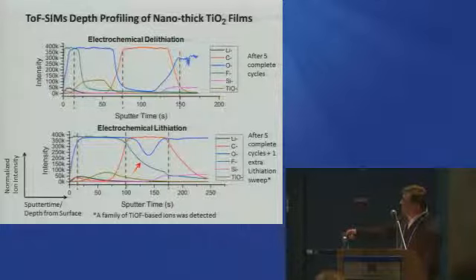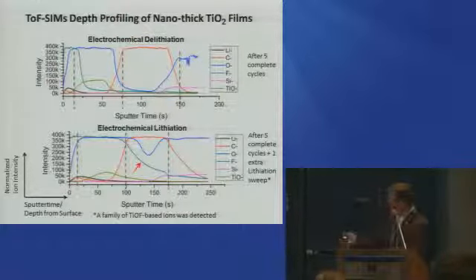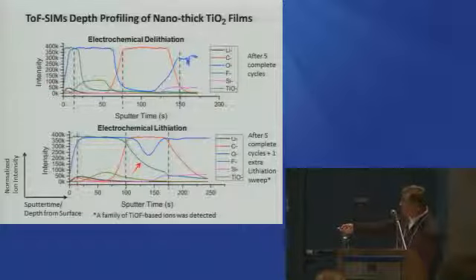If you compare the films that were cycled and then removed under lithiated conditions, what you see is actually there's this large predominant peak, lost my laser pointer, right here reporting on the fluoride content, and it's actually all the way through the TiO2 film and actually goes into a little bit of the carbon. And of course here's the lithium that's also going in, and it's co-localized with the titanium. The other thing that's not reported here is that when we sputter and do mass analysis, since it's time of flight, we can actually get products that look like they're fluorinated titanium oxygen species. So these are titanium oxyfluoride type species.